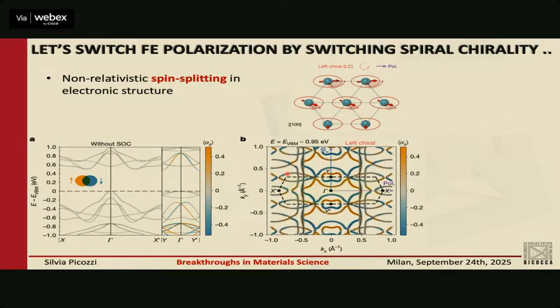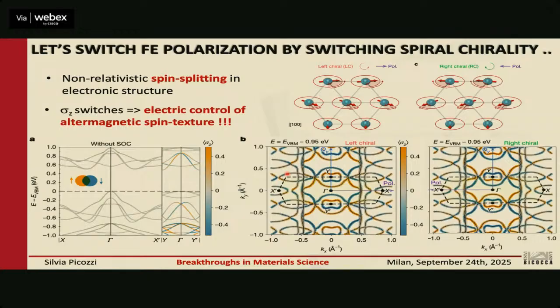But then the nice thing is, if you apply an electric field and switch the ferroelectric polarization, then we know it switches the chirality. And because you switch the chirality, you also switch the spin texture. So for example, here I cut my band structure at a certain energy, and you see that this one is orange and this one is blue. But if I switch the chirality of the spins, this one is blue and this one is orange.